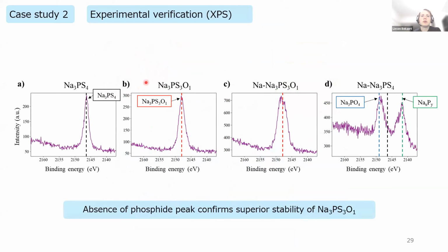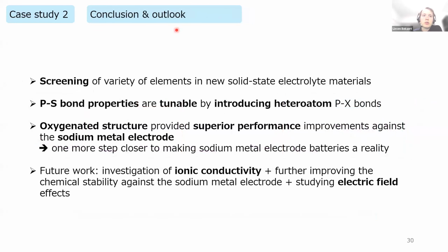And finally, we also confirmed this experimentally using XPS. So you can see when we have sodium and the conventional material, Na3PS4, we have the presence of these phosphides. But when you have the sodium and the oxygenated structure, you do not have this phosphide peak. So this also confirms once again the superior stability of Na3PS3O1.